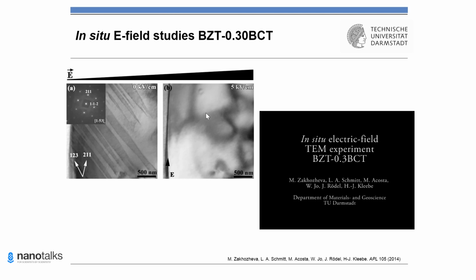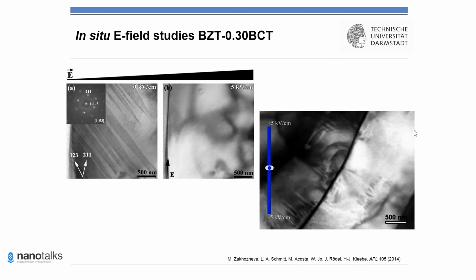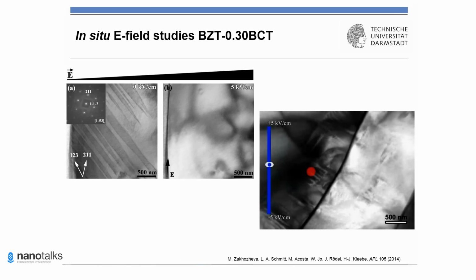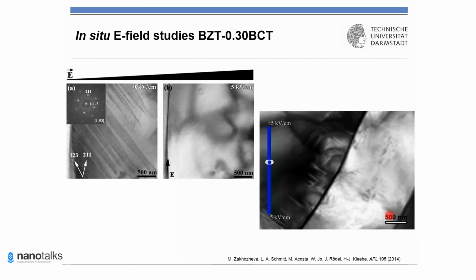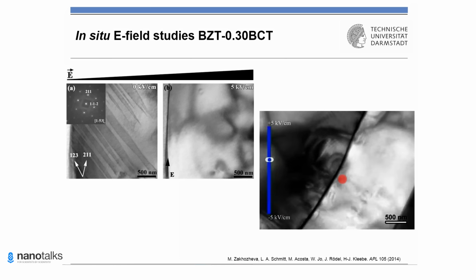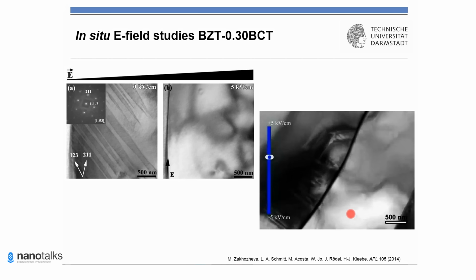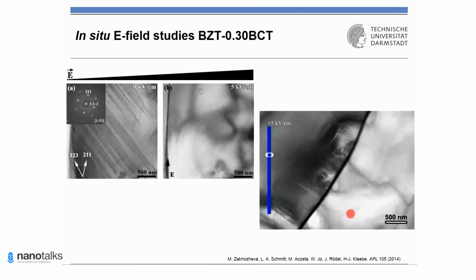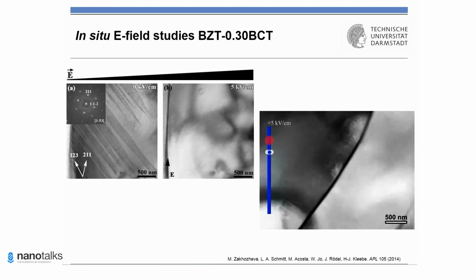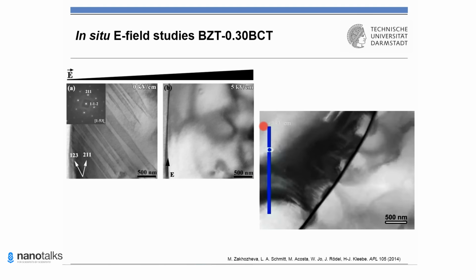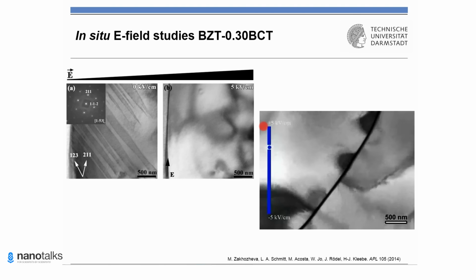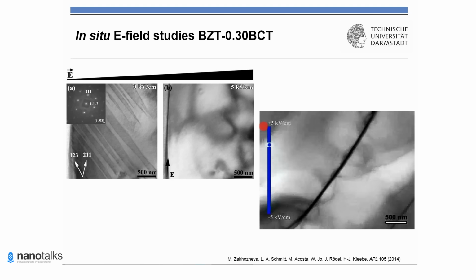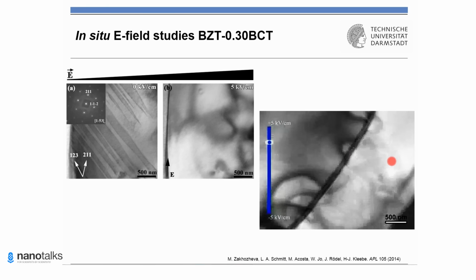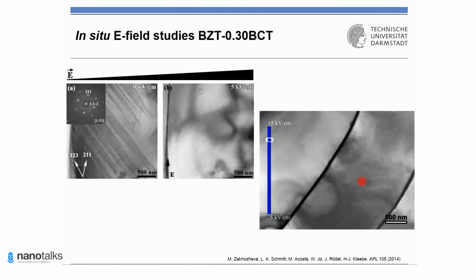Okay, now I would like to show you a video. Here you can see another representative grain of the same composition. The video shows three neighboring grains, and prior to applying an electric field, we see a domain contrast within the grains. With increasing electric field, we can see changes in domain contrast, which indicate a switching of ferroelectric domains. With further increase of the electric field, at approximately 4 kV per centimeter, the transformation from the multiple to single domain state will occur. You see that now the whole grain became a large single domain, basically.